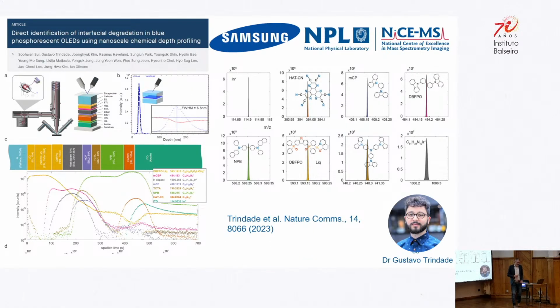So let me switch a little bit now to material science applications. This is an example where we used OrbiSIMS to look at an organic electronic device. So if you have a phone like this, it's probably an organic electronic display. And if you look at one particular pixel, you'll see that it's a very complex organic layered chemistry with hole transport layers, electron injection layers, barrier layers, all of these things to make the device work. The thickness of this is only a few hundred nanometers. So it's very complex chemistry in a few hundred nanometers.